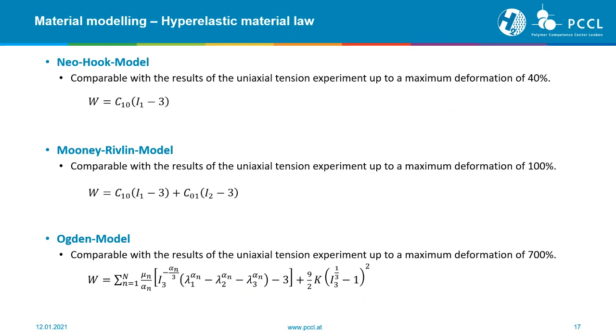However, these are all just basic models which explain a hyperelastic material law. Nevertheless, you always have to think of where the limits of your application are and for what you would like to do your simulation. These are two very important points because, for example, the Neo-Hookean model fits uniaxial tension experiments well up to a maximum deformation of 40%. This means when we have an application where our material is applied up to 500% deformation, then the Neo-Hookean model will not fit very well. Therefore, there are also other models like the Ogden model or the Mooney-Rivlin model. However, as I mentioned, these are really the basic material models.